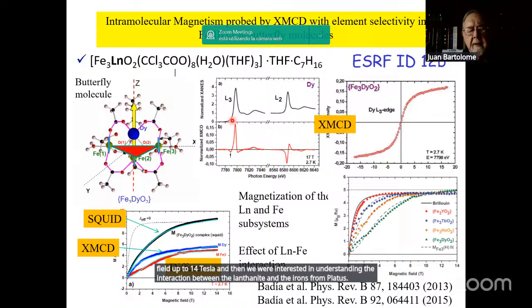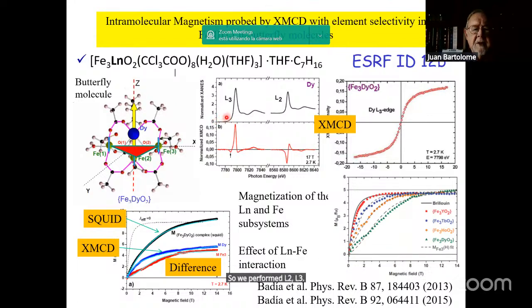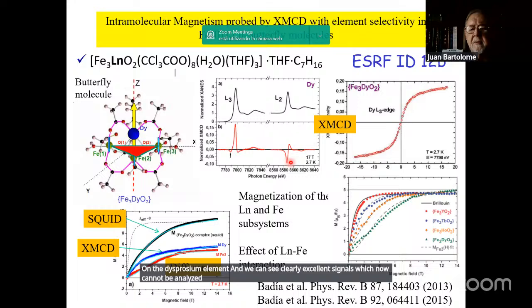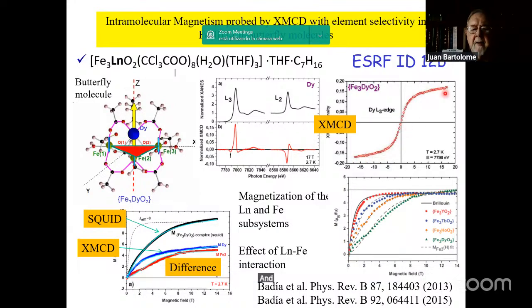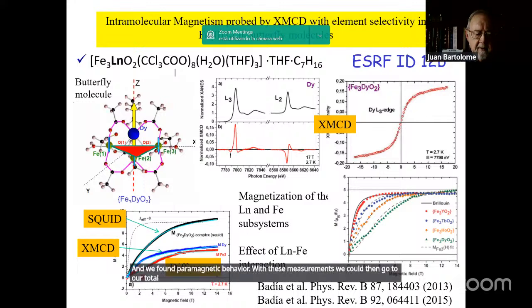So we performed L2, L3 XMCD measurements on the dysprosium element, and we can see clearly excellent signals, which can now be analyzed in terms of sum rules. However, we could measure as a function of field at the top of one of the edges, at the L3 edge, and we found paramagnetic behavior. With these measurements, we could then go to our total spin. Here is represented the dysprosium signal, and from the difference, we could extract the information of the behavior with field